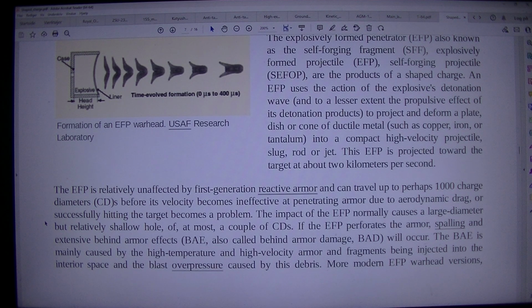The impact of the EFP normally causes a large diameter but relatively shallow hole, of, at most, a couple of CDs. If the EFP perforates the armor, spalling and extensive behind armor effects, BAE, also called behind armor damage, BAD, will occur. The BAE is mainly caused by the high temperature and high velocity armor and fragments being injected into the interior space and the blast overpressure caused by this debris.